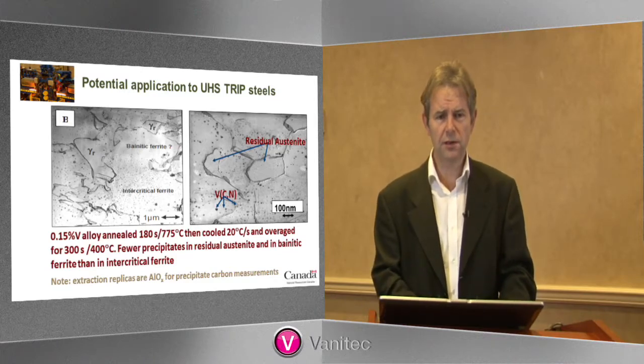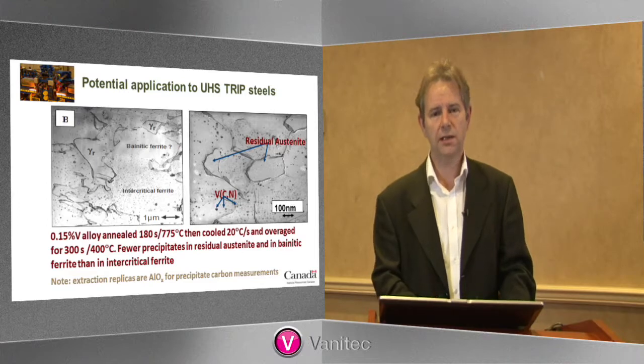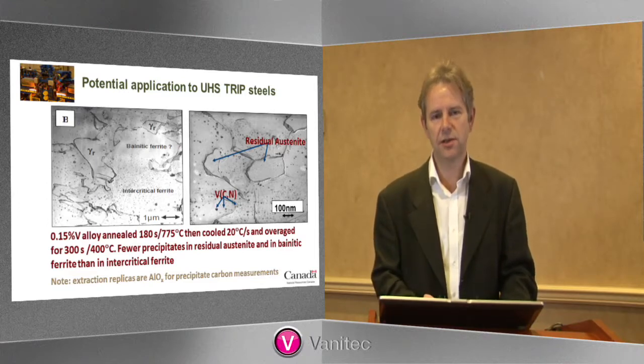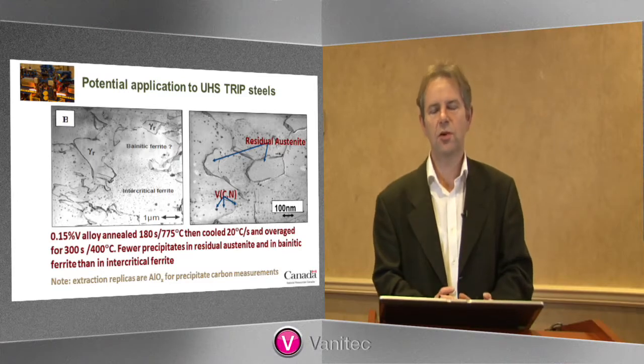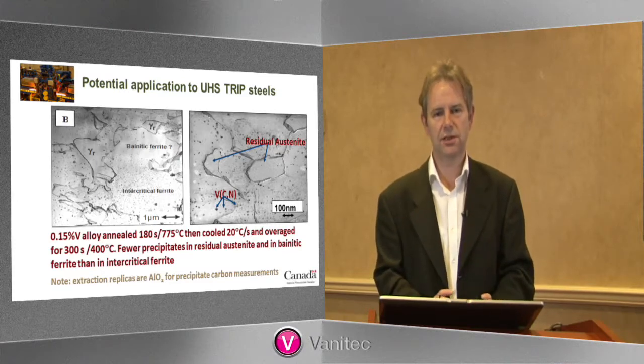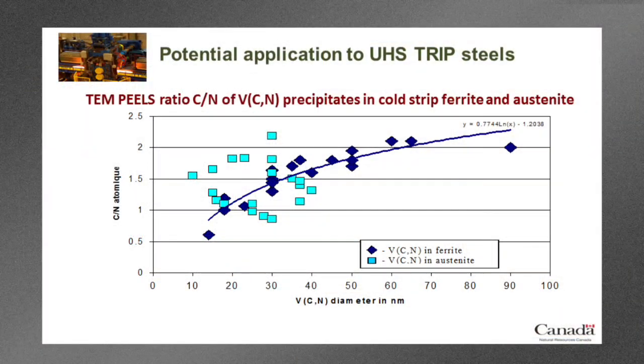Now, we went a little bit further and we said, well, that's very interesting. Why is that happening? These extraction replicas were not carbon replicas, they were aluminium oxide replicas, special replicas that we made to do this particular type of work, because we wanted to see how the carbon and the nitrogen were distributed inside these carbonitride precipitates. So what I'm plotting on this graph here is the atomic ratio of carbon to nitrogen along the vertical axis, along the y-axis, as a function of the precipitate diameter. So as we go higher up this axis here, the precipitates are becoming richer in carbon. Lower down here they have more nitrogen in them.